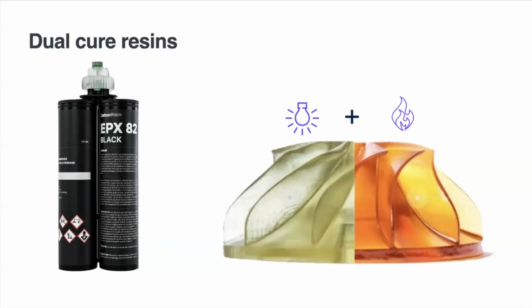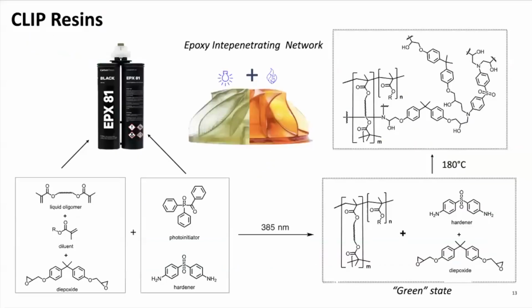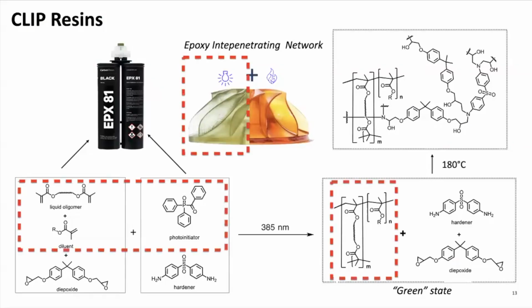Light is not a good way to make most polymers, but it's a good way to shape a polymer. So we basically developed orthogonal chemistry. So we have chemistry that's going to go on with light, and then we have other chemistry that's going to go on by that mixture. And they can run independent of one another, so they're orthogonal. And so just to show you one chemistry slide here, we basically are going to have about 10 volume percent, and only about 10 volume percent of the chemistry is light sensitive, free radically activated. And that will set the shape of the part.